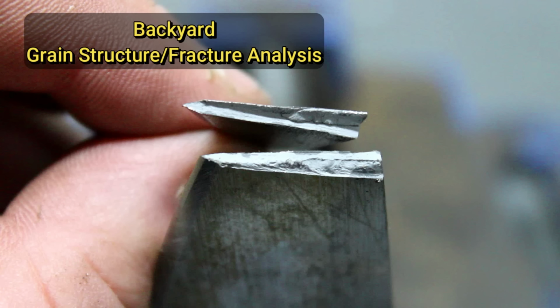The grain structure tells us the quench was solid, and there's no visible grain growth, no large crystalline facets. So we didn't overheat during austenization, and the structure is tight and uniform, which points to a proper martensite transformation. We got a fine silky grain, and that's exactly what we're after. The failure at the tip isn't coming from grain size. It's coming from insufficient temper. That area stayed harder and more brittle than the rest of the blade.